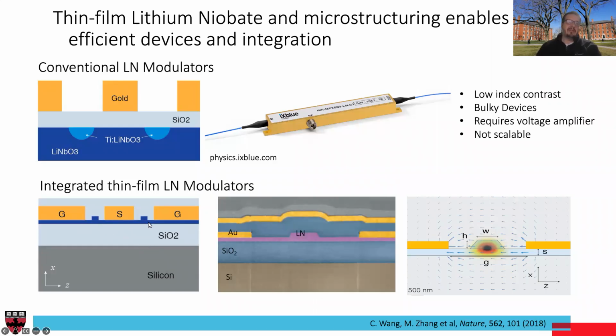Basically, what you have is a blue layer of lithium niobate that has a thickness of roughly 0.5 micron, and that sits on about 2 to 5 microns of silicon dioxide on top of a silicon handle, though the substrate can be anything really. It can be quartz, sapphire, many other substrates can be demonstrated. These wafers at the moment we purchase from a company in China, NanoLN.